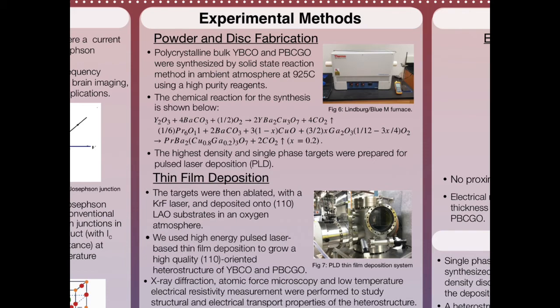Then we deposited an excellent quality 110-oriented YBCO/PBCGO heterostructure using the pulsed laser-based thin film deposition technique at the Oxide Laboratory of UW-Madison. The pulsed laser deposition system uses a high-energy laser to ablate the disks, and then deposit the materials atom by atom onto a template called the substrate for each layer of the device.